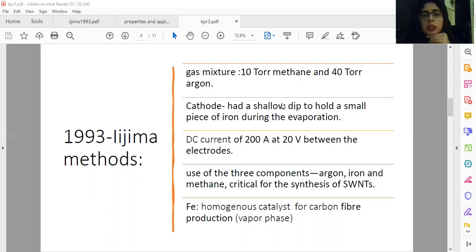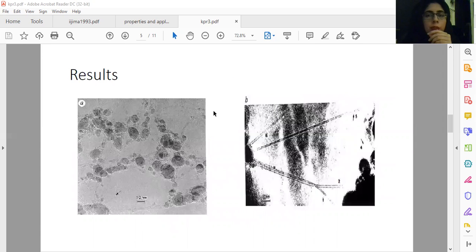For this experiment, the transmission electron microscopy images indicated the presence of carbon nanotubes which were curved and tangled together. These are the results from the paper. In the first one, we can see electron micrographs showing bundles of single shell carbon nanotubes, which are curved and entangled. The dark blobs that you see are cementite particles, which were used to assist the tubule growth. A terminated tubule is indicated by an arrow here. Similarly, we see two terminated carbon nanotubes of different diameters and lengths in this micrograph as well.